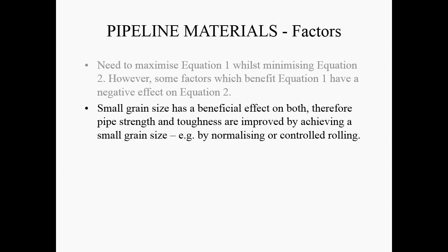If we can achieve that just by making the grain size smaller, we're not adding any alloy elements, so we're not adding cost. We're not changing the material properties and the microstructures and everything. So we've got no real problems when it comes to qualification because we still have the same materials. And so it's a very, very important way to actually go ahead. So small grain size is good. Smaller the better.